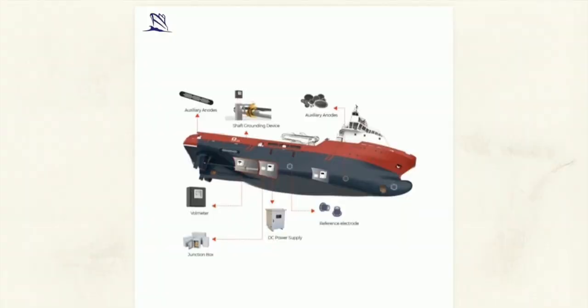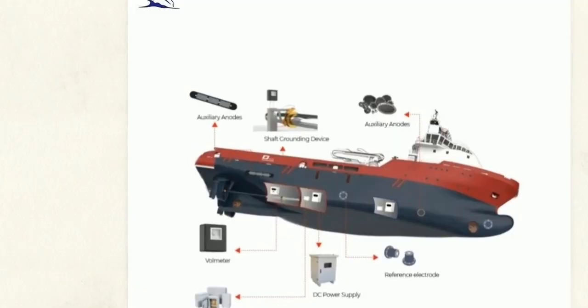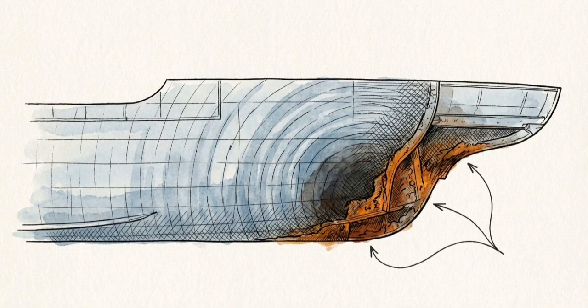This diagram maps the necessity of multi-zone placement. A massive ship requires a carefully calculated array of anodes for uniform current distribution. Complex geometric areas, particularly the aft stern near the propellers, experience high turbulence, requiring highly targeted anode placement to maintain the field. If the current distribution is uneven, localized corrosion will still occur in the shadowed areas of the hull where the electrical field fails to reach. The physical layout of the anodes along the hull is as critical as the electrical power driving them.